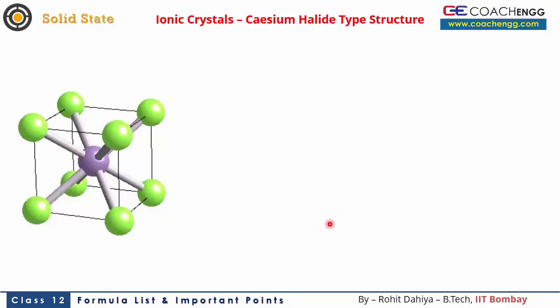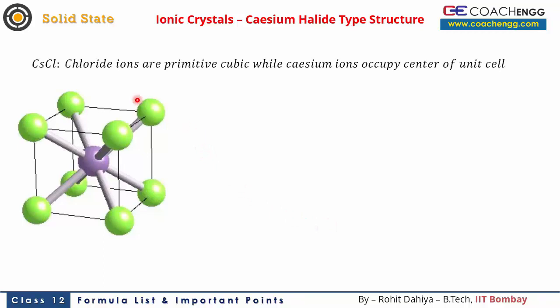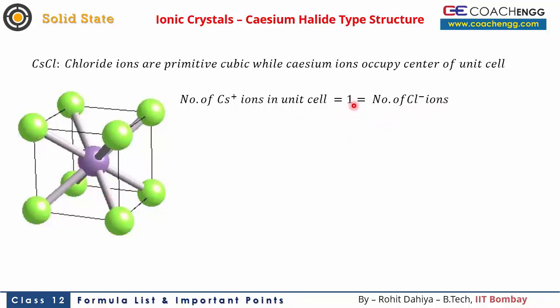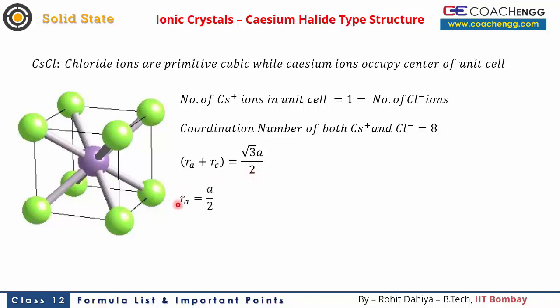The last case is the cesium halide type structure. Cesium halide has a unique structure. Cl⁻ ions sit at the 8 corners, and Cs⁺ ion occupies the body center. Per unit cell: 8 corners × 1/8 = 1 Cl⁻, and 1 Cs⁺ at the body center. Both ions have a coordination number of 8. The geometry gives: r_A + r_C = (√3 × a)/2, and r(anion) = a/2 since the anions at corners touch each other. The cation-to-anion ratio in this case is 0.732, so the body center is occupied.